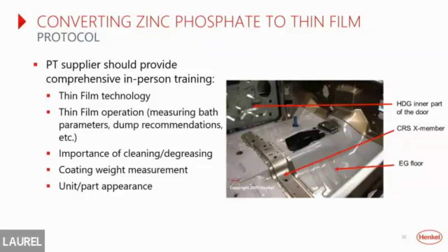Aluminum goes in shiny, comes out shiny. You cannot really see the coating. And a lot of times with cold rolled steel, you may get a bluish tint or an orangish tint, which if it were zinc phosphate, would mean that there was a very bad coating, but it's normal with zirconium. So it's very important to manage a customer's expectations, because what they're going to be seeing is different, and it doesn't mean it's bad. And that's a big thing to deal with.